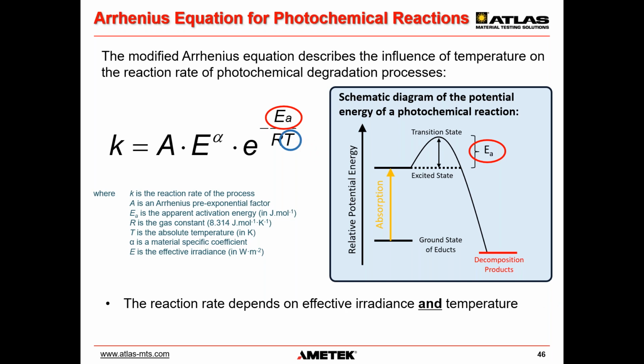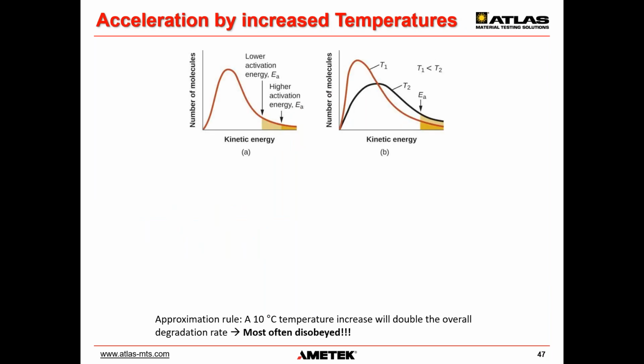With low activation barriers, there are many molecules with enough energy to overcome this barrier, so the reaction is going fast anyway, and an increase in temperature has a small effect. An increase in temperature increases the amount of molecules with higher energy, translation energy or vibration energy. More molecules are able to overcome higher activation barriers. Thus, this has a big effect on reactions with high activation energies. This is not an on-off mechanism. Of course, it is related to the probability distribution of a molecule having a high enough energy to react, but that's an advanced topic. Only a little bit on that.